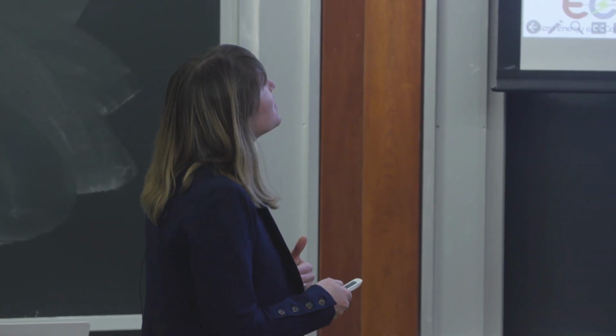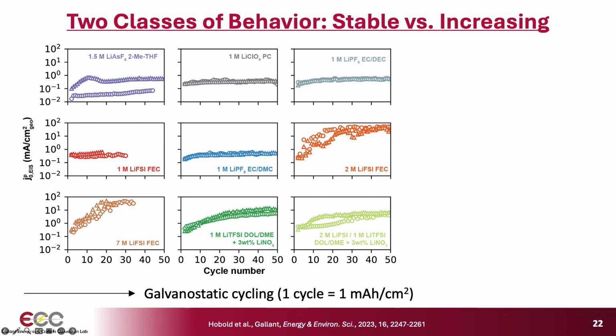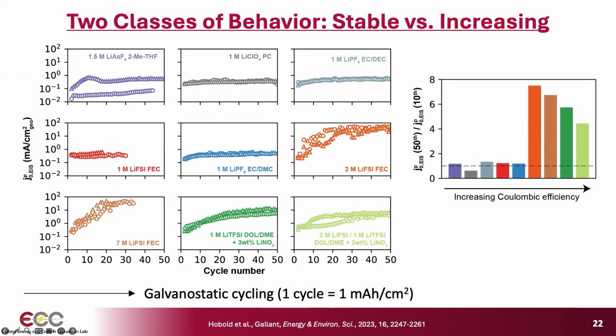Now, there was an interesting observation in our data. I mentioned that we were cycling and probing the J naught over cycle number. We actually found in some cases, like these first 5 electrolytes shown here, that the J naught value that we measured was pretty independent of cycle number. This graph shows the ratio of the value measured on the 50th cycle to that measured on the 10th cycle. And for this first set of systems, there's pretty much one descriptive value that we can use to describe exchange